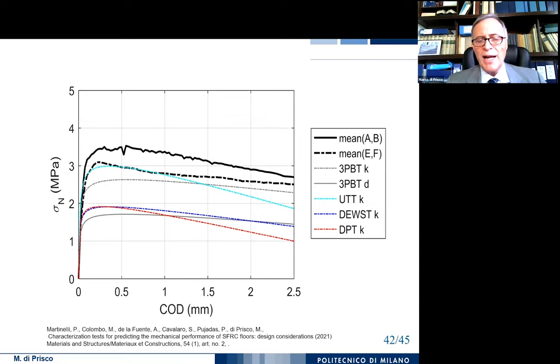And finally, we can evaluate the behavior with reference to the nominal strength versus COD for these beams. And from this, you can see that if you look to the design value, which is the gray one, you always have a safety coefficient, with respect to the behavior of the beams obtained by changing the casting position, closer to more than two.